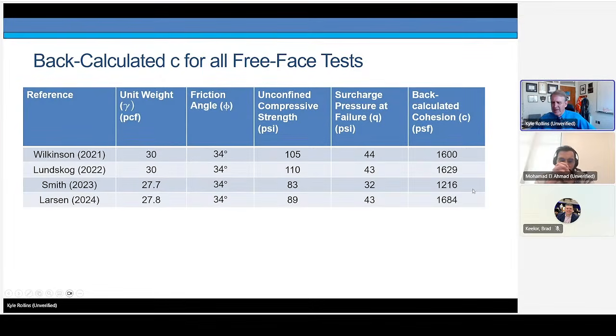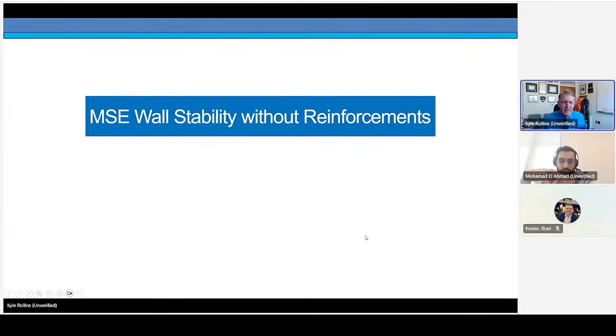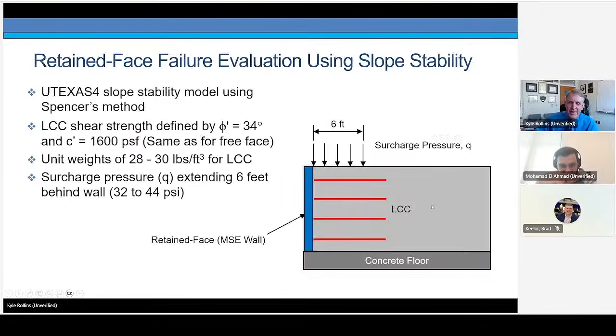So this is the range, a lot of them in the 600 to 1600 PSF range. This one test where we had some lower strength concrete was in the 1200 range. So somewhere between 1200 and 1700 PSF was our back calculated cohesions. Then we went to analyze the wall stability with reinforcement.